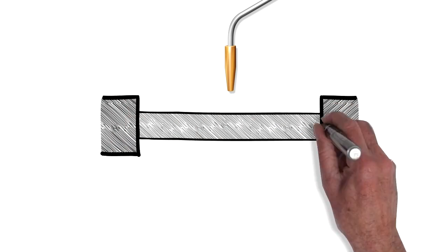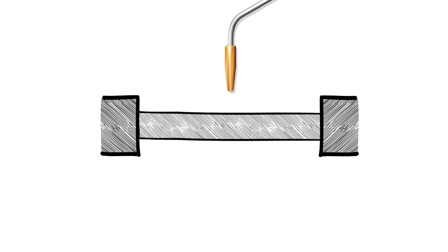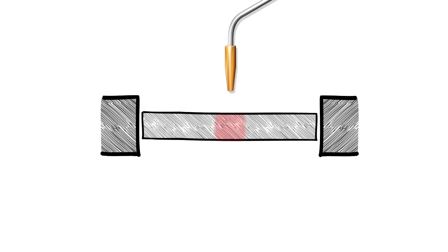When the metal bar is constrained at each end however, it cannot expand. So at the point where heating is occurring, at the plastic temperature range, it is upset and plastically deforms. Now when it cools, the metal bar shortens in length.